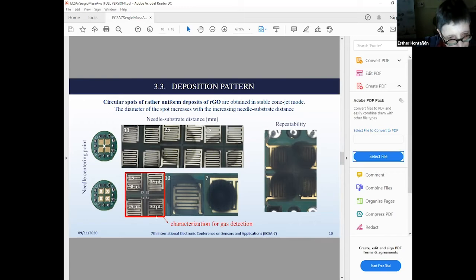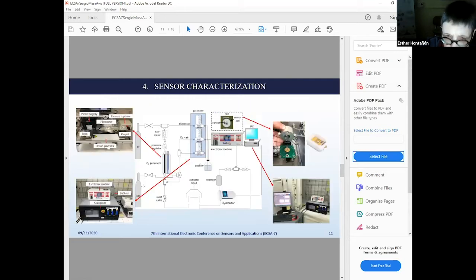And then we observed that this case was the first one in which the resistance of the 4 sensors went down to values within the measurement range. They also show acceptable sensitivity to the target gases, nitrogen dioxide and ozone, at sub ppm level. So these are the results I'm going to show you. In other cases, for instance, maybe the surface density of RGO was too low, and in some cases the coverage of the whole surface was only partial, so sometimes the resistance of the sensor is not within the measurement range, or the signal is very weak, or there is a lot of noise. So this was the first one that really succeeded. And these are the results I'm going to show you now.